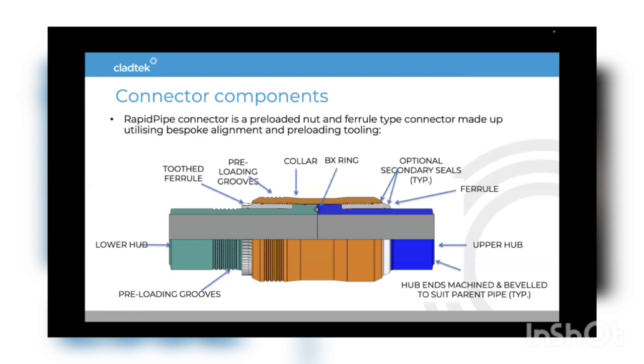But we have optionally the ability to install secondary seals between the ferrules, both the left and right ferrules, between the ferrules and the collar, and the ferrules and the hubs. We also have a further option of being able to install seals on the upper hub, on the lower hub, if we want to do external pressure tests through a port in the collar. So you can see just either side of that BX ring the slots there for secondary seals. We don't think that's very likely a requirement, but we did use this facility when we were doing external pressure testing during the qualification process.